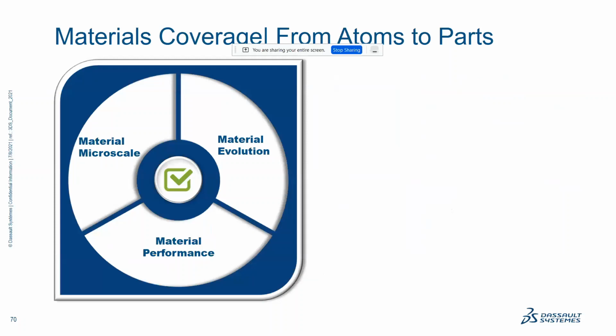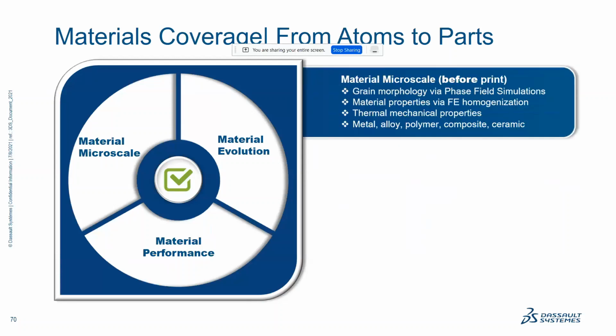To achieve all this, I talked about two key frameworks. One was on the heat flux modeling. The second was on the mesh toolkit. The third aspect is on the material property, how it is predicted. So here we take a multi-scale approach, right from the material behavior from a micromechanical standpoint to the performance at the post solidification standpoint. So at the micro scale level, that is before the print, we need to do phase field simulations which are handled internally, and then the material properties are obtained through internal homogenization, which will give us a quick map of the properties for the overall domain.